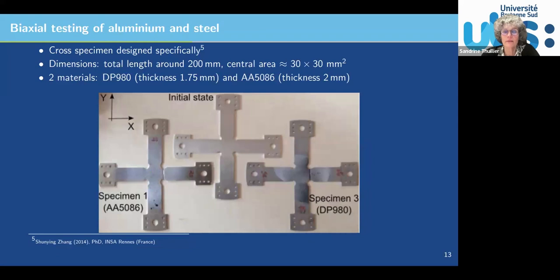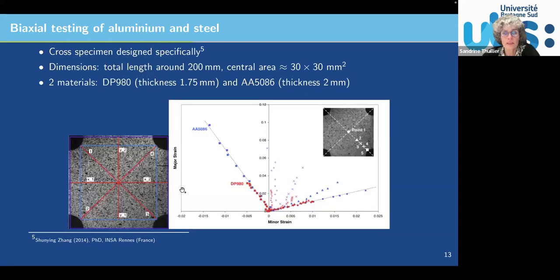So I will now focus on some examples in order to show you what kind of results can be obtained. My first example is about biaxial testing. In this case, it was performed with both an aluminum alloy and a DP, dual phase, steel. This cross shape will lead to a non-homogeneous strain field in the center here. And just to give you an idea, we used digital image correlation to capture the strain field, but we didn't use the whole information over the area of interest; we used only information along a line in order, I would say, to simplify the problem.